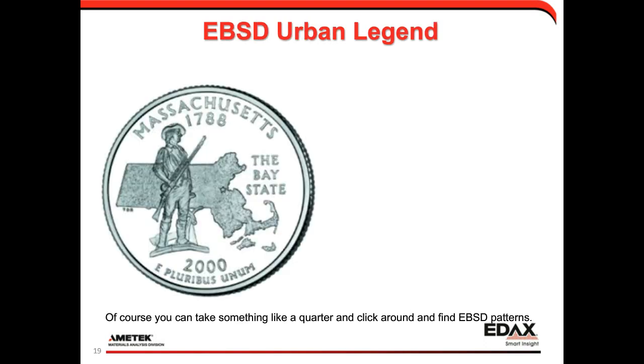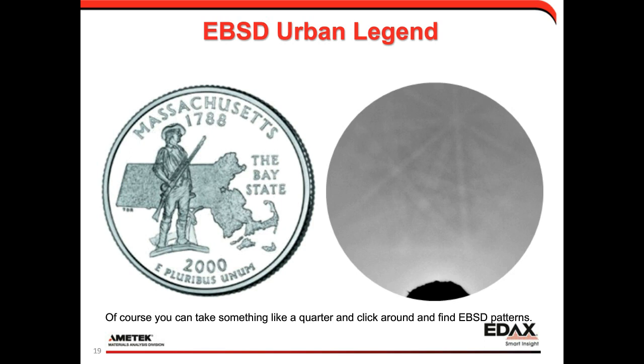So this is just a little schematic, and I've called this an EBSD urban legend. But you can take a material and put it in the SEM, and put the beam on it. And if you look hard enough, you'll often find some sort of a diffraction pattern. Here you can see a pretty weak diffraction pattern, but it's certainly indexable. We see a little bit of an artifact there due to some amount of topography. And this is just from a coin I took out of my pocket and threw in, and I could get a diffraction pattern. So sample preparation is not always required to get a pattern.